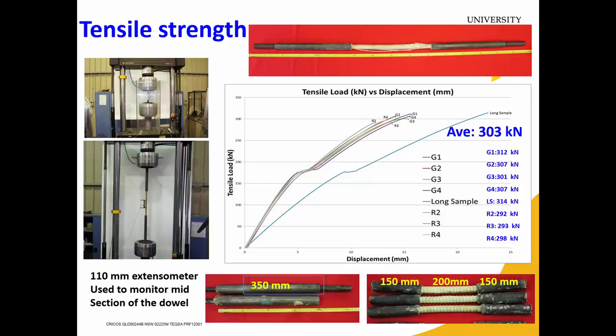So let's start with tensile strength. Based on accredited standard, the sample is first cut to 500 millimeter. 150 millimeter from either side is encapsulated inside a special cylinder, and then the whole assembly is positioned inside the tensile testing machine and subjected to tensile loading at a predetermined rate. The value of tensile load against displacement is recorded as shown in this figure.